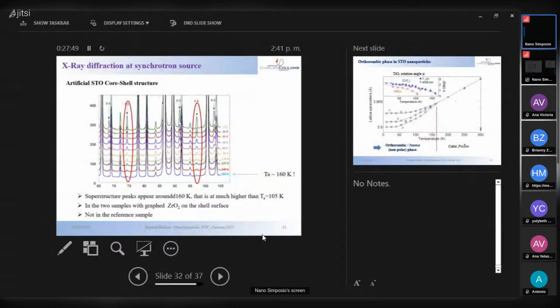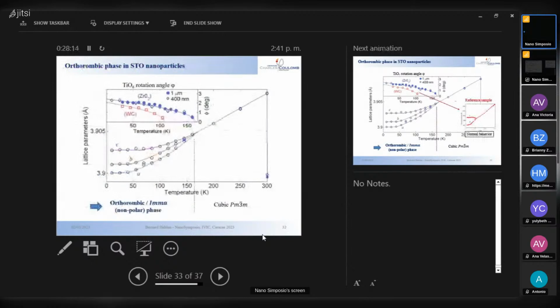And if you do diffraction on that, you see that in the artificial core shell structure, the structural transition develops at 160K instead of 105K, which is something quite interesting. And only in the artificial STO core shell structure; in the normal one, the structural transition develops at 105K as usual. If you plot the lattice parameters here, and first, for example, the angle, you remember the rotation angles phi of the octahedra. For the reference samples, it goes down at 105. For the two artificial samples, it goes down at 160.